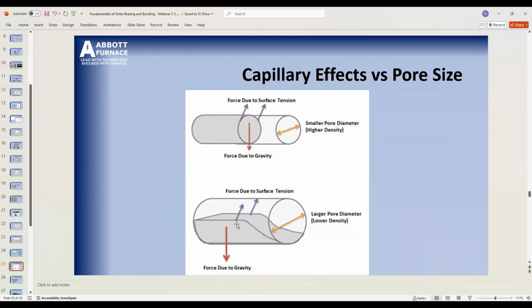So instead of filling the whole pore and pulling all of that filler metal through, when I have a large pore, I only have a small amount. So even though I'm carburizing, even though I have flux, I'm doing all these things to try and control it, I don't have control because the viscosity of my filler metal is overriding all of the tools I have.